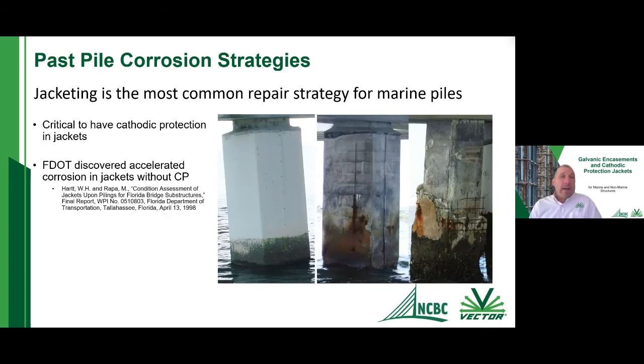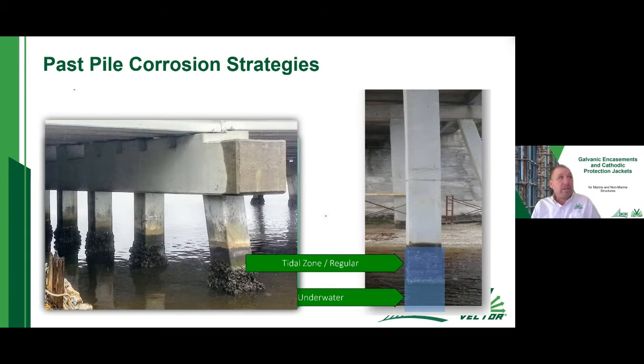I showed you just a few of the past jackets that were done without any sort of cathodic protection. There have been a number of studies done on jackets or concrete jackets that have been placed around piles, and they found that corrosion still occurs behind these jacket systems without CP on it. So a number of owners, entities and states have now included in any jacket or jacket overbuild situation that they want to include cathodic protection in it, just because this corrosion continues.